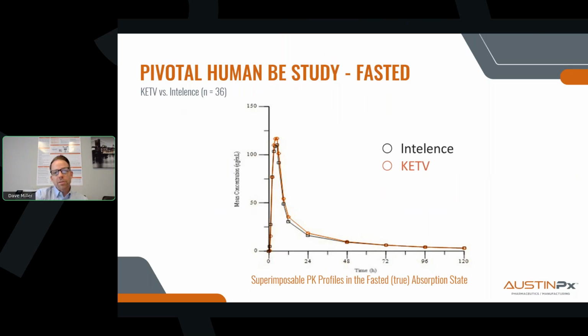Importantly, it was noticed as well that the variability between the subjects was lower for the KinetiSol product. That's one of the issues with Intelence being a highly variable product. So that really indicates tighter control over dispersion, homogeneity, and release kinetics achieved with KinetiSol. So achieving full bioequivalence for this challenging compound and ASD formulation that we thought was nearly impossible to thermally process is a really powerful statement about the capability of KinetiSol.